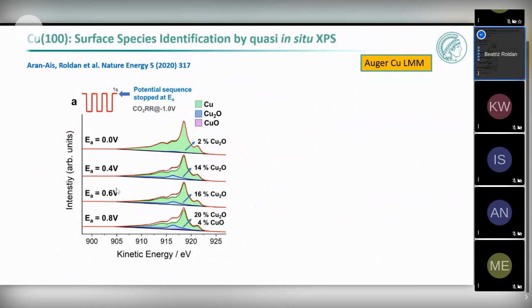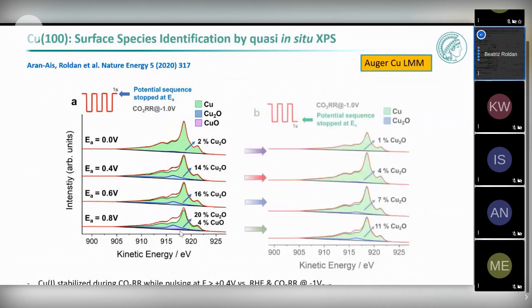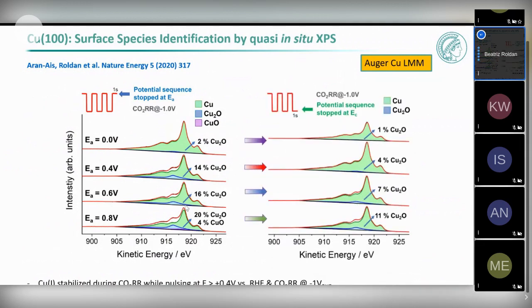And when we go to the potential where we know that we are oxidizing the surface, you can see here in the copper Auger data that you don't only have metallic copper, this is in green, but you also have a small amount of copper 2O, so between 16 and 20%. Now the question is, what happens if we go to -1 volt here only for 1 second? Does this copper plus remain at all? And the answer is yes. If you went initially and you had about 16 to 20% copper plus, you see reduction, of course, when you go to -1 volt, but it's not completely gone. You still see between 7 and 11% of copper plus coexisting with metallic copper. And this is going to be enough to make significant changes in our selectivity.